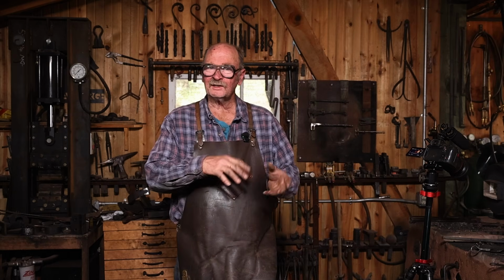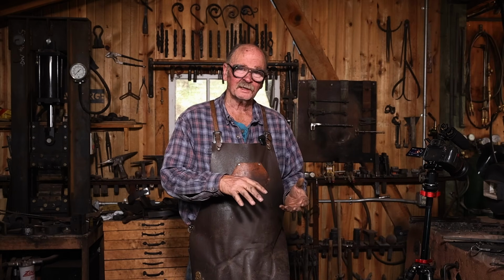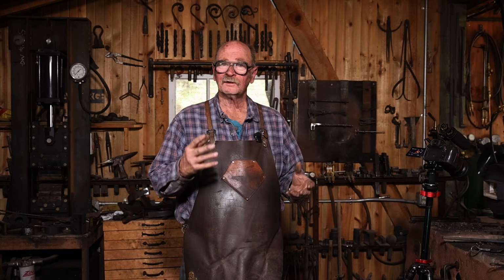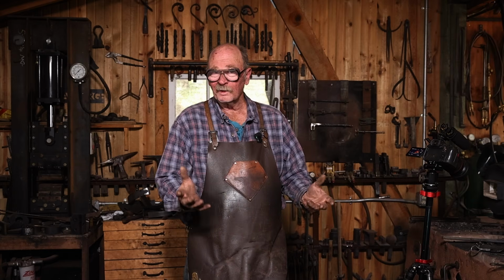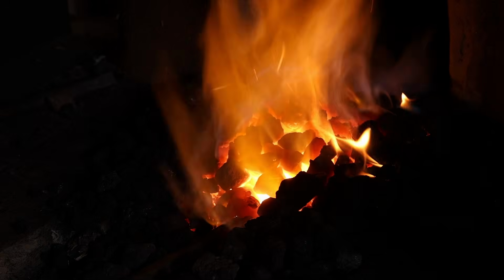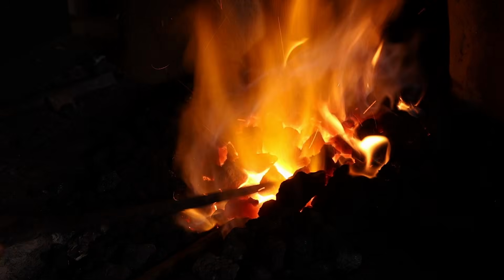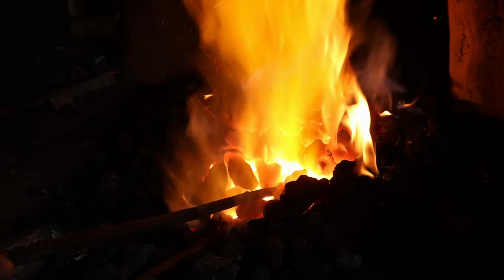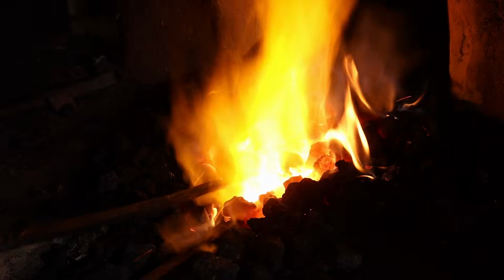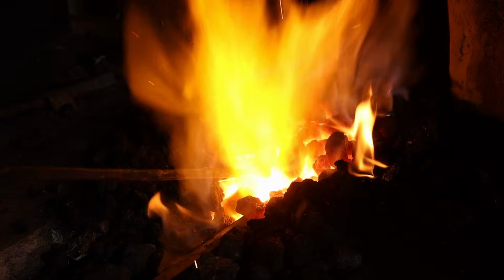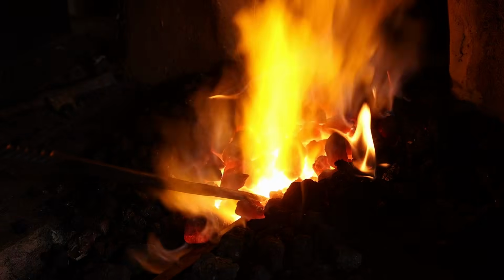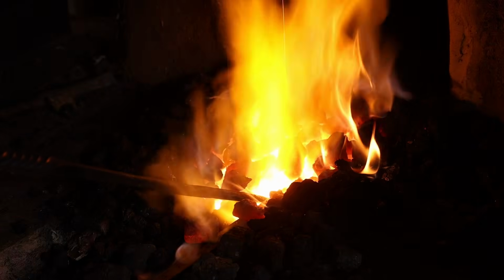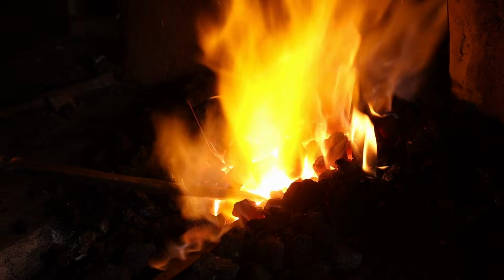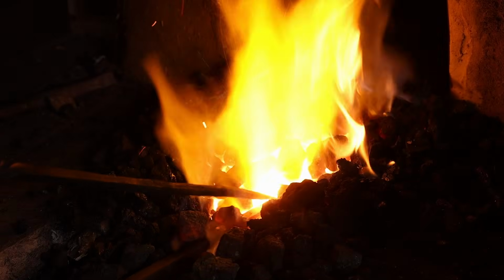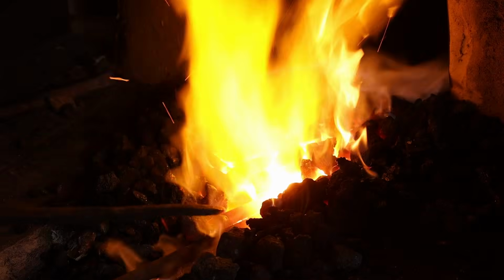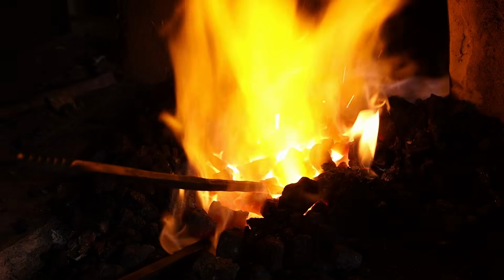And it pays to gently turn the material in the fire as you're coming up to heat to get a good even heat. Just try not to be too energetic with it so you don't knock all the flux off. A little poker helps push the coal or the coke away, and you can see down in there. I don't know if you can see it on the camera or not. You can see the bright orange yellow heat down here to the left, and the material is not that color. When the material starts to disappear in the fire, you're probably at welding heat.